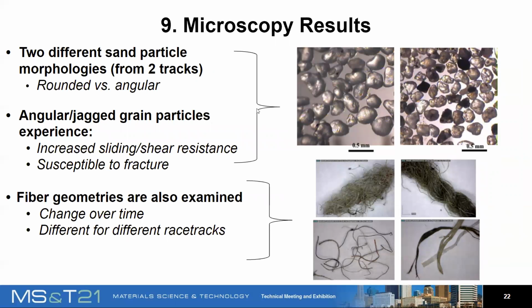And here are our microscopy results. On the left, as you can see, we have more rounded and angular sand particles compared to the one on the right, where we have more jagged particles. The jagged particles have increased sliding and shear resistance and are susceptible to fracture, compared to the rounded particles, which tend to last a little longer and are stronger, but just need to be replaced more often.